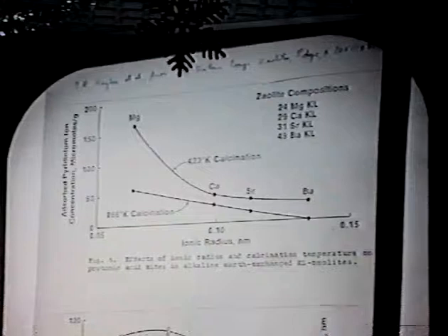Why is that? Because if you put alkaline earths in most zeolites, they may neutralize the acidity of the anionic host, but then they hydrolyze water and add a proton back, and they create acidity. Well, if you look at the structure, there are these normal channels, but then there are these small cages off the main route, as it were, cancrinite cages. And in fact, when you calcine at this higher temperature, the barium moves into these cages.